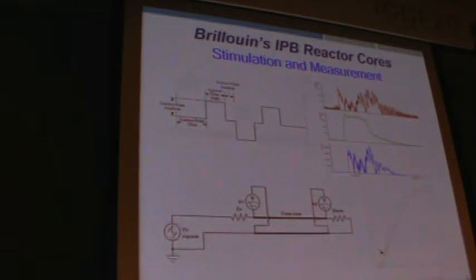Okay, yes, this is an idea of what their pulse looks like. It doesn't look anywhere near that symmetrical. The pulse width is in the hundreds of nanoseconds, and the separation time could be 10 microseconds. So it's probably less than 1% duty cycle. And we control the voltage, control the repetition rate, and things like that. And by being able to control all of that, we can have constant pulse power. So the amount of power going into the nickel is held constant.